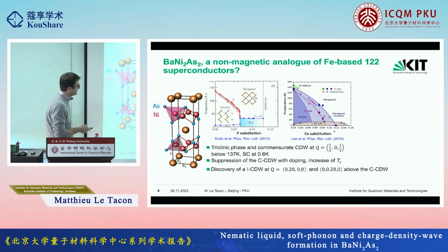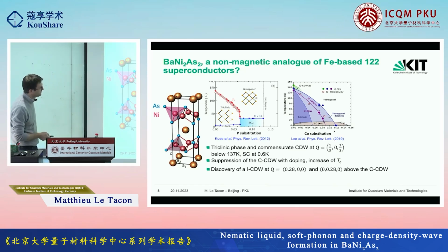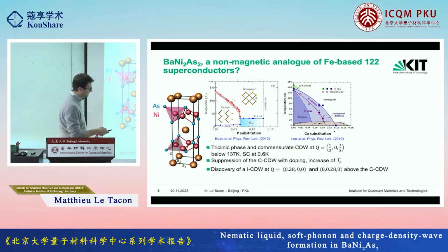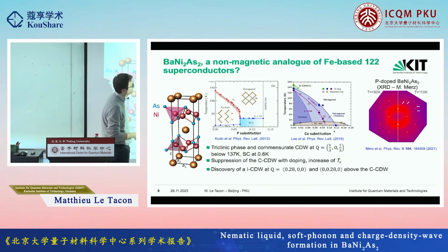but it's interesting. Now, more recently, the group of Peter Abbamonte published this result where they showed that just above this triclinic transition and this commensurate charge density wave, there was another very small regime with an incommensurate charge density wave. And when this paper came out on the arXiv, one of my colleagues came to my office and said, well, that's embarrassing. We have had this for a very long time.